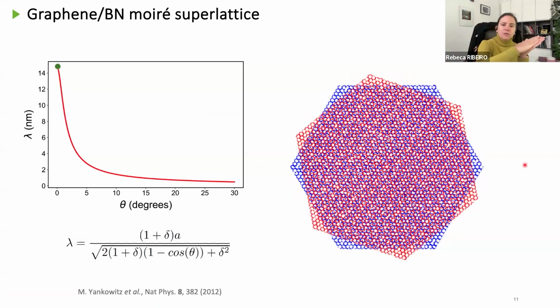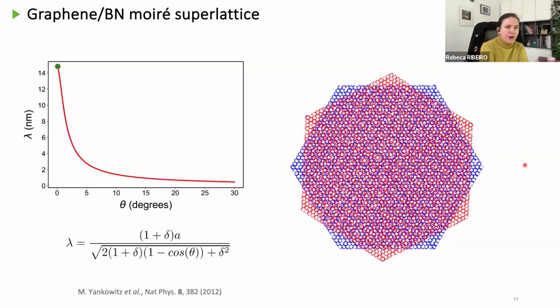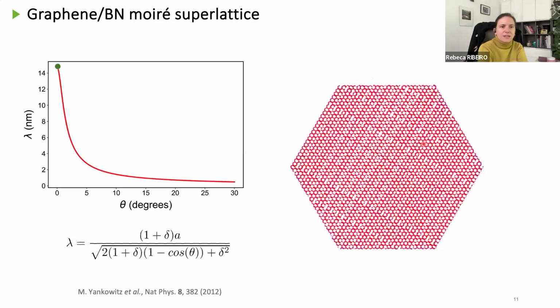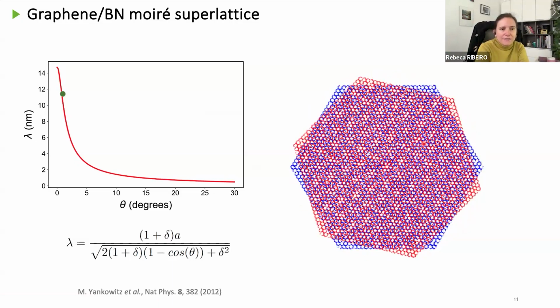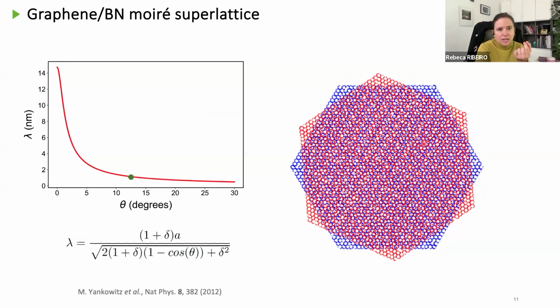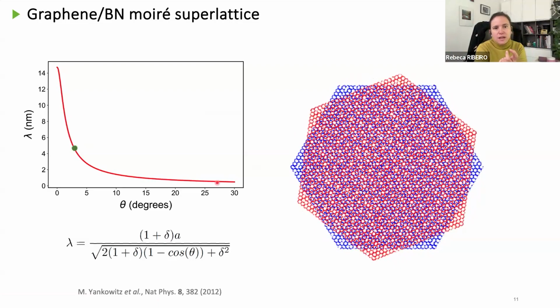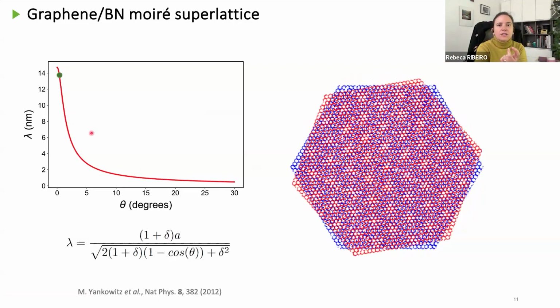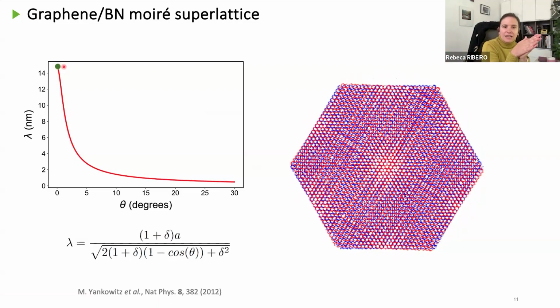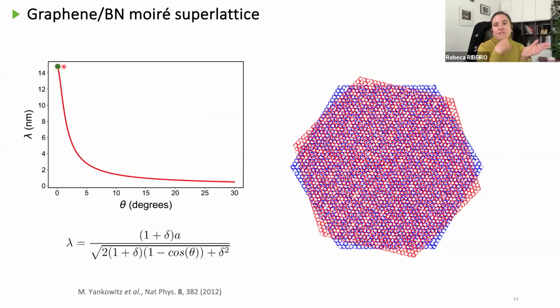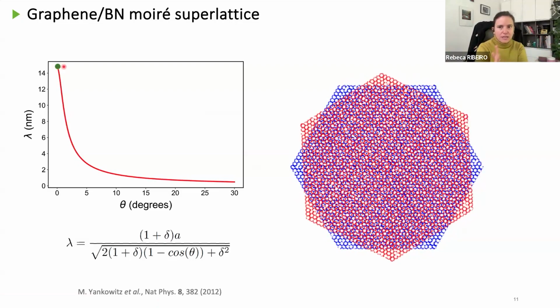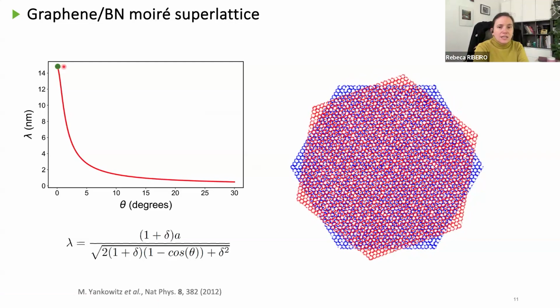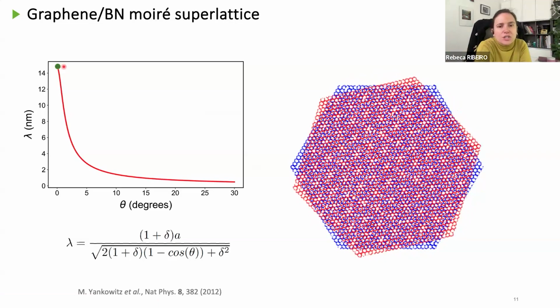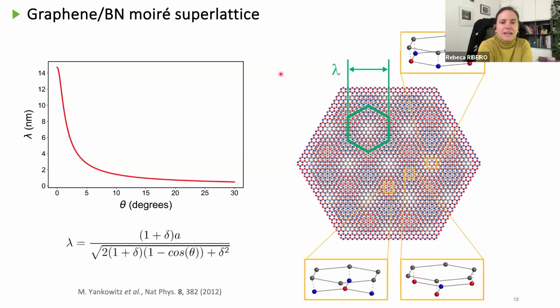So this moiré will strongly depend on the angular alignment, as you saw in the previous animation. And you will have the length of this moiré strongly decrease with the angular misalignment, and then it will strongly increase as you realign. So it will be periodic. Every 60 degrees, you will have this moiré. So the moiré structure, in fact, comes from the fact that not every carbon atom is going to have the same environment now.